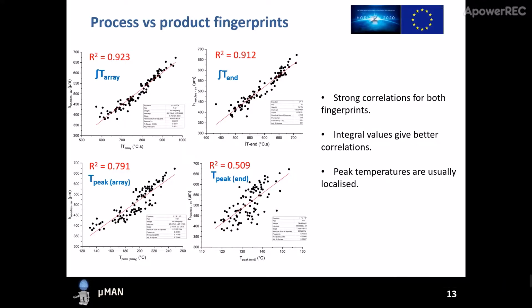So after manufacturing and quality inspection of the parts, we have our process data, and we will write some LabVIEW scripts for extracting process fingerprints like integral values and peak values, peak temperatures, and things like these. And then we plot correlation plots, scatter plots for seeing if there is any relationship between our process fingerprints and product fingerprints. So in that case, we have temperature process fingerprints taken from thermal imaging. We have integral values from the 6x6 array and towards the end of the cavity, and also we have peak temperatures